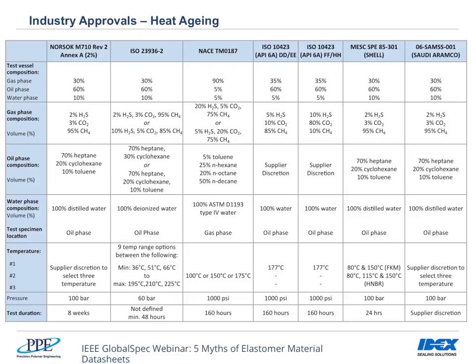As noted before, for every 10 degrees C increase in temperature, we double the rate of chemical reactions. Therefore, if we reduce the temperature, we slow the chemical reactions down, and they can be slowed down sufficiently enough to pass the test, almost irrespective of what material goes into it.